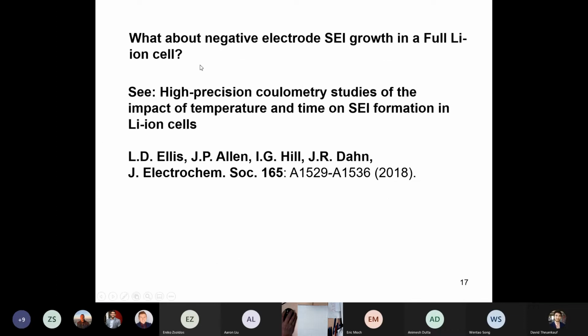So those experiments were made in half cells, so lithium metal and graphite. So what happens to the negative electrode SEI growth in a full lithium ion cell? Well, it turns out to be basically exactly the same, but you can monitor it by looking at the capacity fade of a full cell. In the half cell, like I showed you with lithium against graphite, there is no capacity fade. The capacity is constant. The irreversible capacity just keeps getting bigger and bigger. So this paper by L.D. Ellis is a study of looking at the impact of temperature and time on SEI formation in lithium-ion cells.